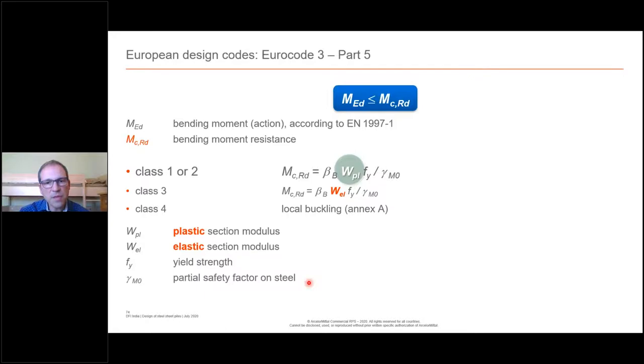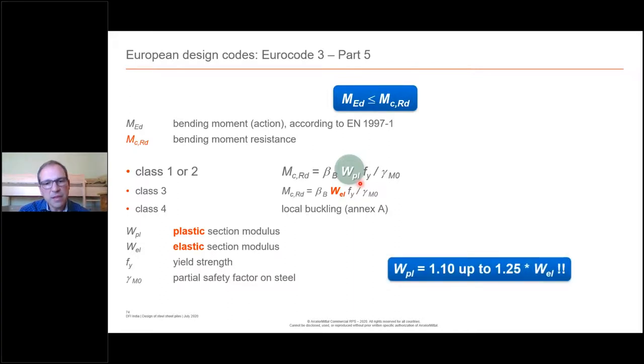So an interesting thing about the new Eurocodes is the classification. Sheet piles are classified in class 1, 2, 3, or 4. It's like in the United States, like compact, semi-compact. And if you have a class 1 or 2, you can use the plastic section modulus, with the same formula, instead of the elastic section modulus. And this is quite interesting, because the difference of the plastic compared to the elastic can be up to 25%. So this means that just switching to the new Eurocode, you could save up to 25% on a sheet pile wall.